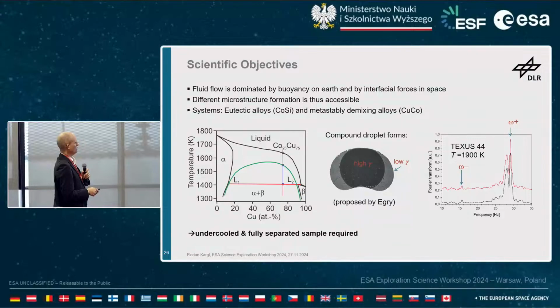So you undercool below the liquidus, this black line here, and then you hit a binodal and you start to demix this system into 2 liquids in the undercooled state. So eventually you might start to form this kind of compound droplet, consisting of liquid 1 and liquid 2. And then, if the system is still not crystallizing, if it's in the undercooled state, you are able to measure interfacial tension according to a method proposed by Egry.